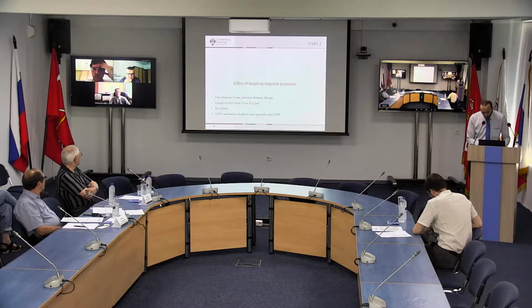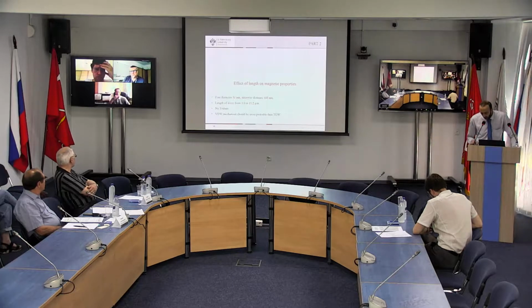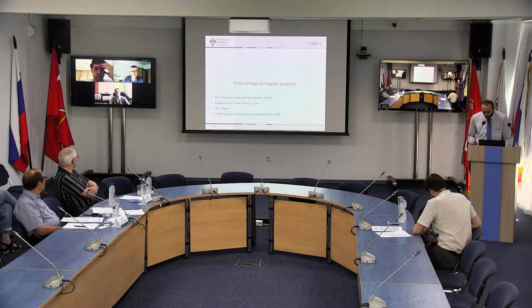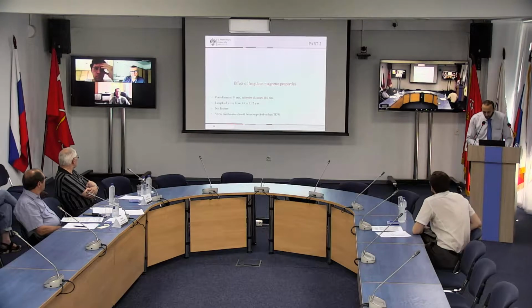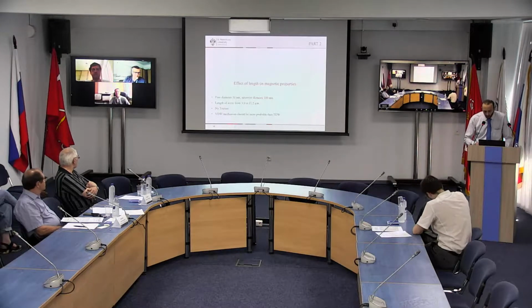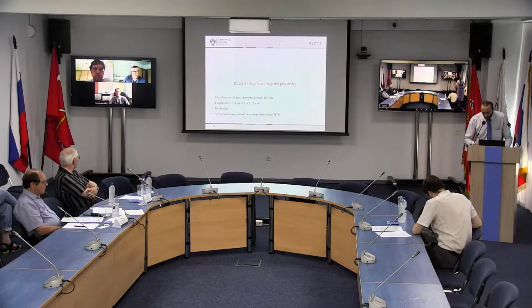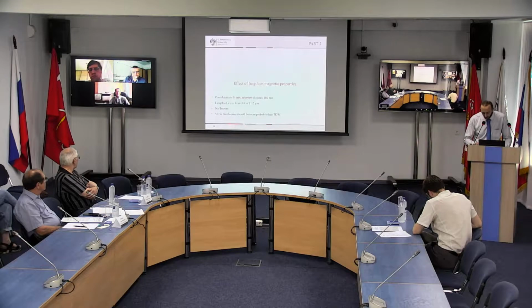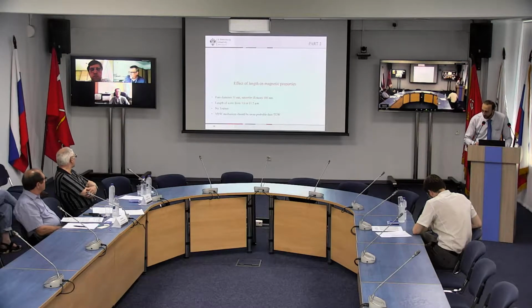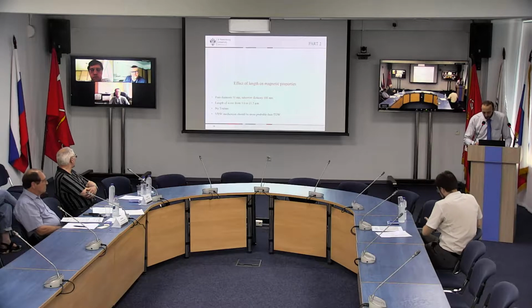Further, to the second part. In order to understand deeply the role of shape anisotropy and interaction in iron nanowires, a series of samples of different lengths was produced, additionally to decrease texturing and to go closer to vortex domain wall motion, depending on the ratio between the diameter of the wire and the critical diameter determined by the material, which is equal to 7 times the exchange length. The diameter was increased for this series to 50 nanometers.